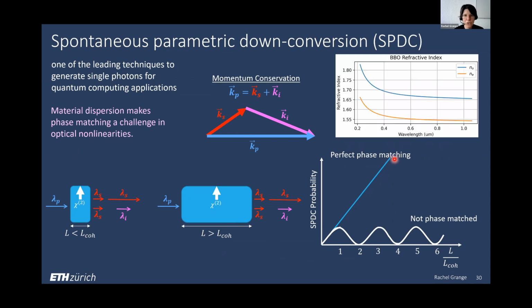And there are many ways to try to beat this problem of phase matching. For instance, in bulk, you take BBO crystals. You may have seen that kind of setup, and I'll show you afterwards what it looks like in your laboratory. Those BBO crystals are birefringent. They have the ordinary and the extraordinary refractive indices that are wavelength dependent.